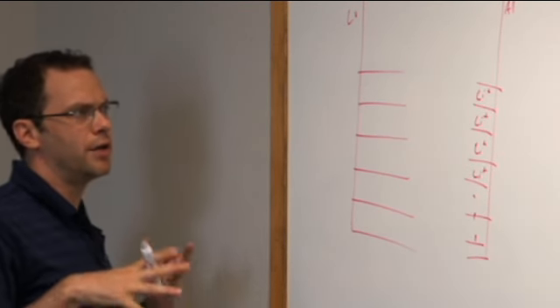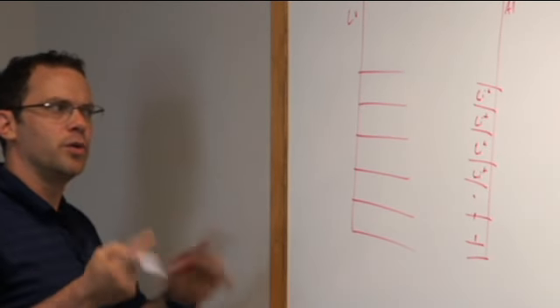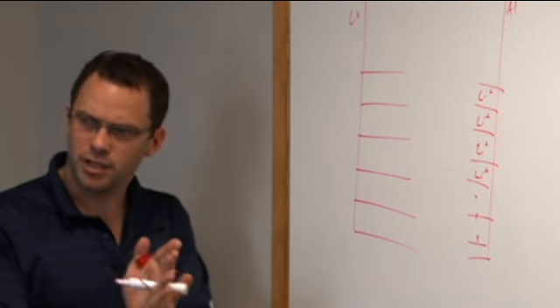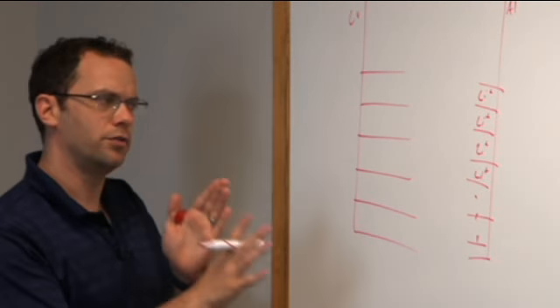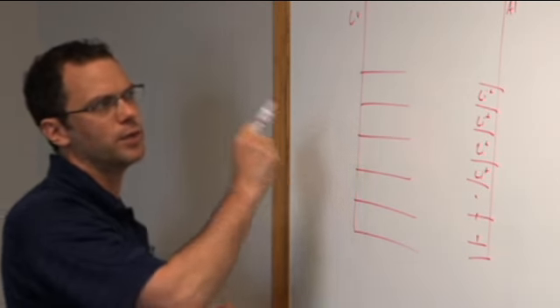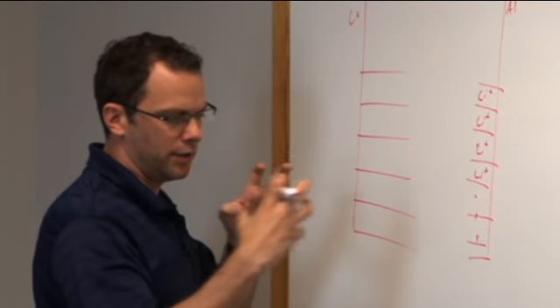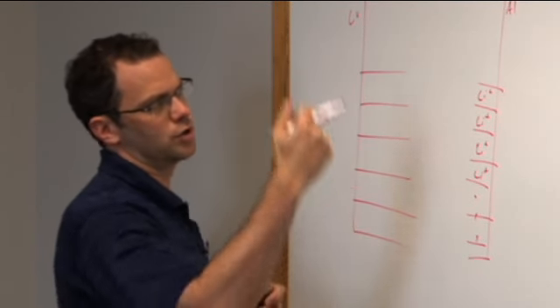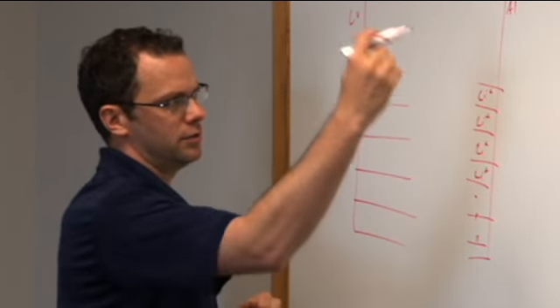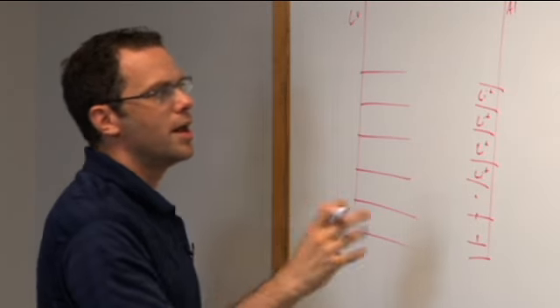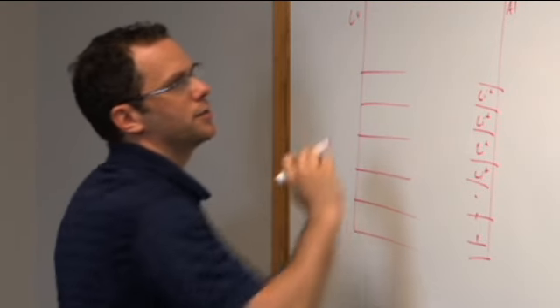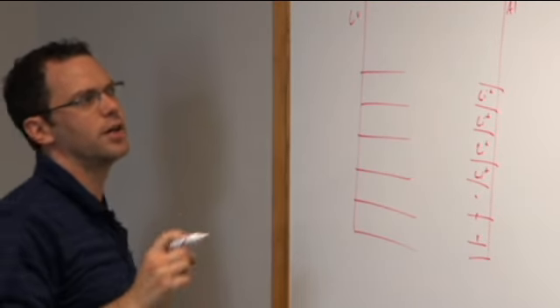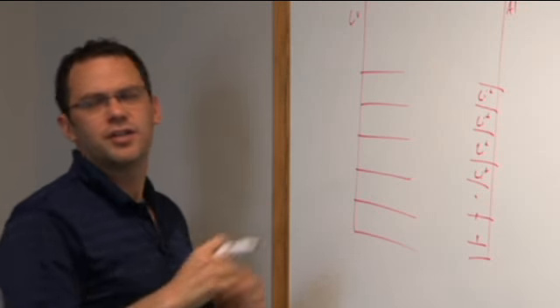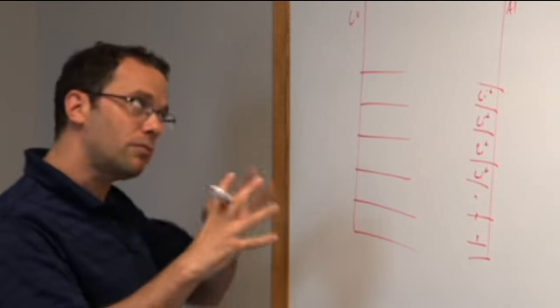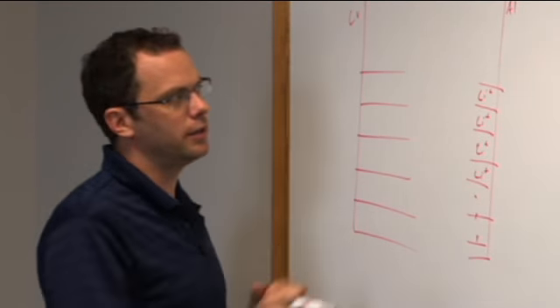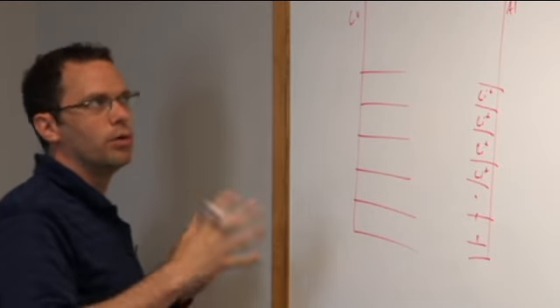It's not a nickel metal hydride battery where you are sort of doing a phase change on the surface of a plating, or you're stripping a material onto a known electrode. You are instead having this relatively well-defined crystal structure with lithium that lives at these different very well-defined points. And what makes this material interesting, it's called an intercalation material, is that when you remove the lithium, it doesn't change its structure that much. It can take lithium in or give it out without altering very much.